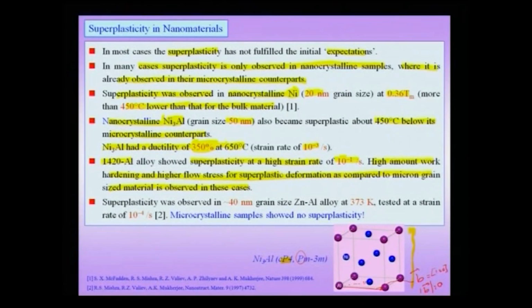Another interesting example is in the case of superplasticity in the 40 nanometer grain size zinc aluminum alloy, and this example is interesting because this alloy showed superplasticity at about 373 Kelvin, which is a very low temperature, and the strain rate is of course small. But the important thing here is that the microcrystalline samples, that means the bulk counterparts of this, showed no superplasticity.